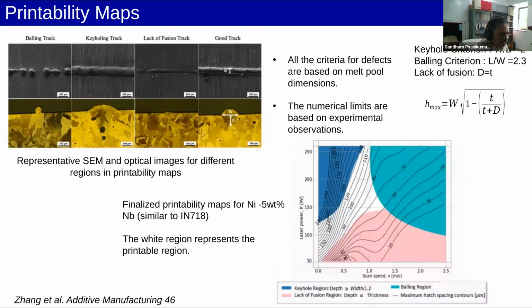Okay. Now the tracks are shown here as an example. So visually you can make out, when you make a single track, whether the defect is a balling kind of defect, or a lack of fusion defect, or a keyholing defect, or whether it is a good track. So you can actually do the sections to understand which of the 4 regimes of the map we are operating in, and thereby we can calibrate our specific consumable and specific processing conditions with this map. And after that, we can operate in the region of safety, that is basically the white region, which is the good printing region.